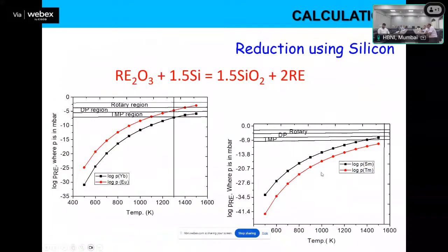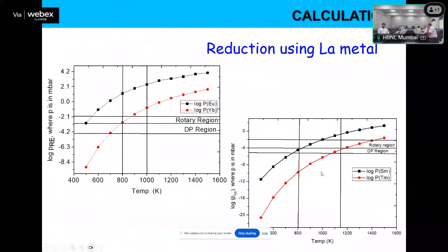And if you do reduction using lanthanum metal, lanthanum is also a rare earth, and it is also used for reduction of samarium oxide, ytterbium oxide, etc. If you plot this particular plot, for europium, even less than rotary, a water pump can work if you use lanthanum. And for ytterbium, rotary vacuum is good enough for working at 800 Kelvin. Similarly, for samarium and thulium, where the temperature and pressure conditions are very severe, at around 1200 to 1300 Kelvin you can use DP vacuum to get the samarium or thulium out.